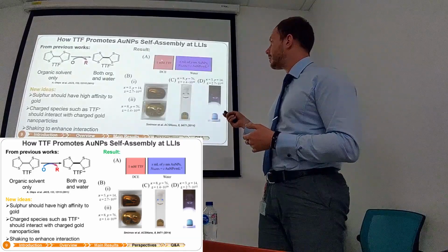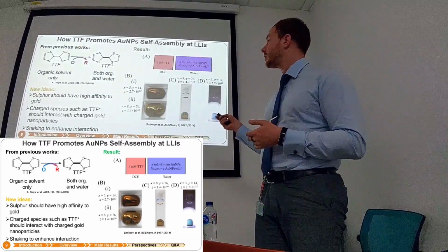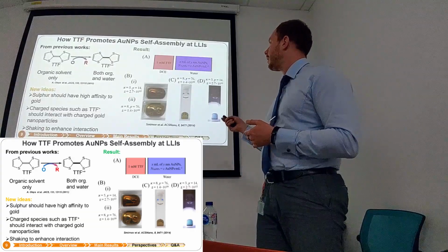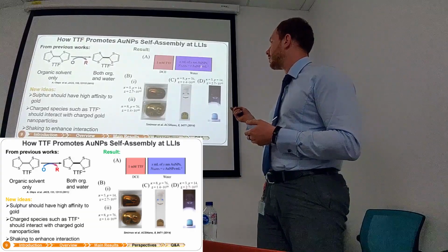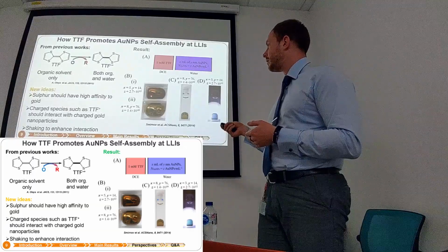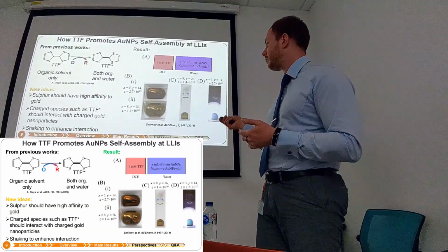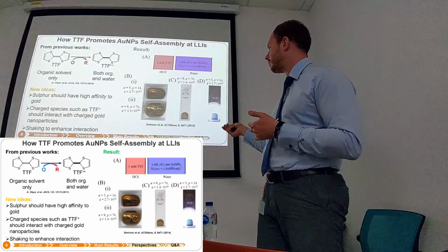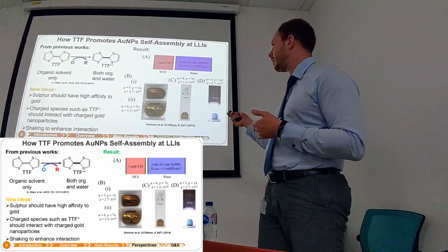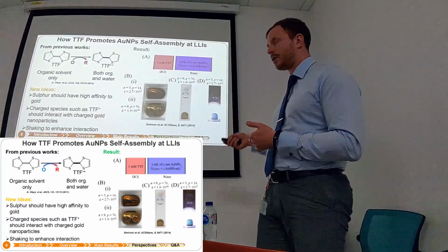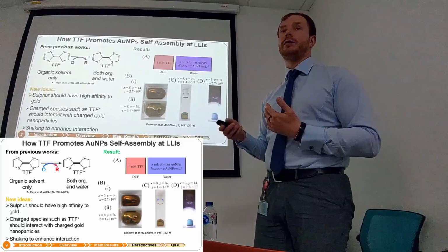As a result, we took a 1 millimolar TTF solution in dichloroethane. The water phase was with nanoparticles, and after shaking, we finished with these nice films. One is a mirror film for very big particles, and for small particles, a kind of filtering film.